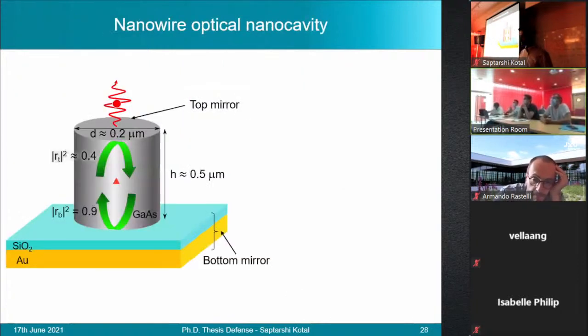The proposed device consists of a cylindrical gallium arsenide nanowire segment that is sat on a silica gold hybrid bottom mirror, which has a modal reflectivity of around 0.9. The top flat facet acts as the second mirror of the cavity, thanks to the contrast of refractive index between gallium arsenide and air. And this results in a reflectivity of the order of 0.4.